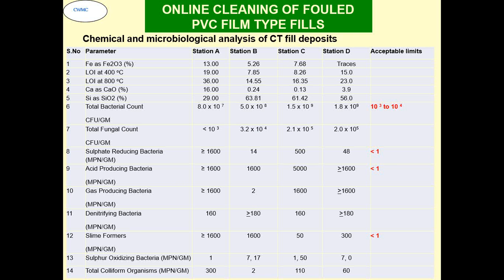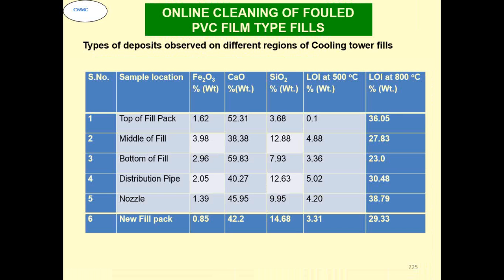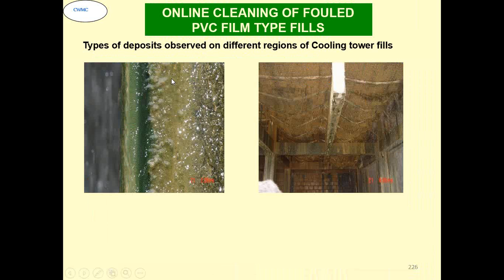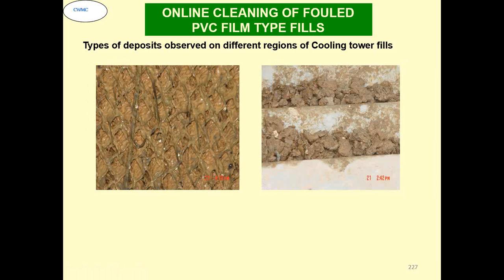This is a typical microbiological analysis of the fouling that was observed at different stations on the PVC films. You can see all of them are very high in level. See, this is the kind of thing. You can see this is thick algae. These are the fouled films. You can see the structure has deteriorated because of the weight. In this case, the 20 kg original fill pack weight had become 180 kg in about 6 months' time. This is the kind of fouling which is there. It mostly consists of mud or dust or dirt, whatever is there in the system.